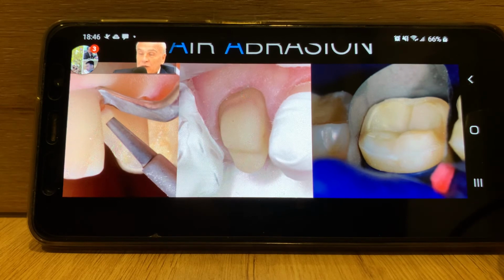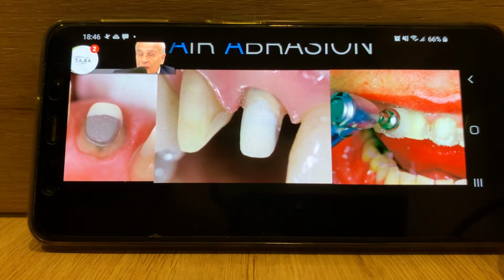Although you want to use a rubber dam whenever you can, sometimes it's not possible, especially when I'm using conventional cementation, and I still use this, but you can adequately protect the gingiva. And if it's very low pressure, even if the particles do hit the gingiva, they will not penetrate it, they will bounce off. So that is not a problem. It never has been. I've been doing this for more than 25 years. You can see here that with the air abrasion protocol, you will roughen basically, but you will clean any surface. On the left side, you can see that it is metal and composite and dentin, and all these materials can be very well cleaned with air abrasion.